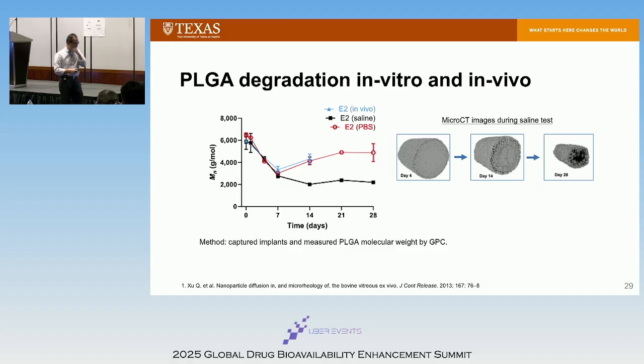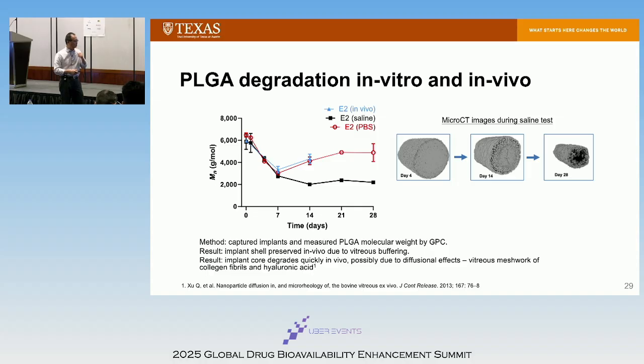But what happens in the eye, it's not just water, all right? There's a network of collagen fibers and hyaluronic acid. They actually slow down the diffusion of oligomer. We believe one way to do in vitro dissolution for the vitreous implants is to run in a viscous dissolution media. Don't run just in the water. Like if I run the phosphate buffer at high viscosity, you can have a polymer in there to slow down the diffusion of oligomer. That may be bio-relevant and also bio-predictive.